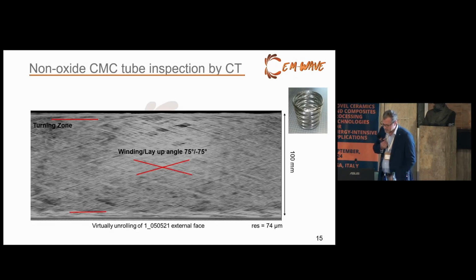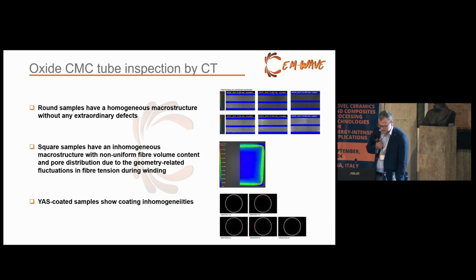But in the pyrolyzed state you can't do it, because the 5% residual carbon does not hold your system. It will just fall apart without any additional matrix. So in this case, it was necessary to keep these winding zones. But after the CVI, the silicon carbide infiltration, we were able to cut these turning zones off.